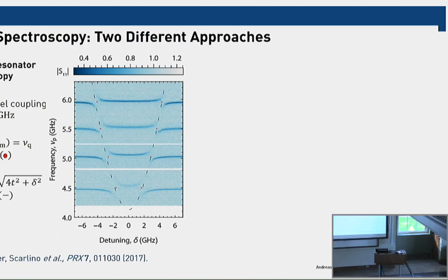Okay, so what else can you do? One of the nice things about this high impedance resonator is that the resonator is now tunable by a magnetic field. And so rather than changing the bias points of your semiconductor nanostructure, which typically has some challenges associated to it, of the sort that Dan asked about, you can now tune the resonator frequency. And so here you see a combination of 4 different measurements where the tunnel coupling of the quantum dot remained the same, and we've changed the detuning and then measured anti-crossings with the high impedance resonator at 4 different frequencies. And this you can then use to map out the quantum dot energy level spectrum, and you see this hyperbolic dependence that was discussed before.